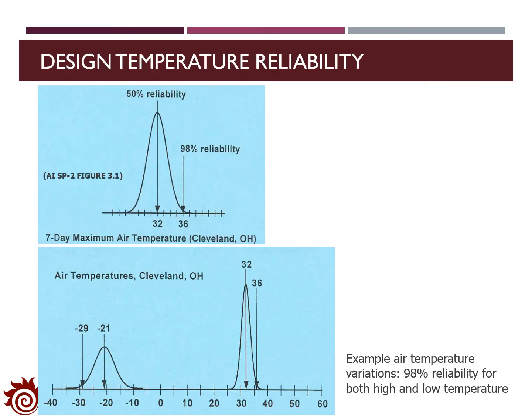In the selection of asphalt binder, we not only need to determine the temperatures applied for the performance grade, but also need to specify the reliability. In general, the reliability is defined as the percent probability in a single year that the actual temperature will not exceed the design temperature. A higher reliability means that the selection of the asphalt binder will be more reliable, and there will be lower risk for the material to fail. Now let's see how we can define the reliability for the asphalt binder in the performance grade.